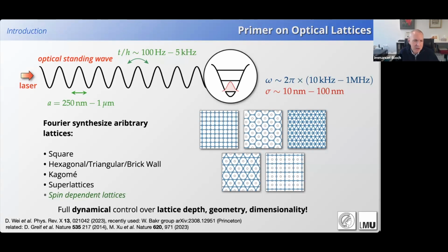And that's, of course, very nice, because we don't have to synthesize a new material to study new properties when we want to study a new crystal structure. And since we know that the crystal structure plays an essential role in the physics, and also the dimensionality of the problem, we're in a very good situation to be able to change between configurations at the push of a button. At the top, you see a few typical energy scales and length scales of these atoms in optical lattices. You see the typical spacings. They are, of course, on the order of λ/2 when you interfere 2 laser beams, so typically in the micrometer range. Then there's the hopping scale, the tunneling motion between lattice sites. And if you think of an individual lattice site as basically a harmonic oscillator, then you have trapping frequencies in the range of 10 kilohertz to a megahertz, and ground state extensions of 10 nanometers to about 100 nanometers in the system.